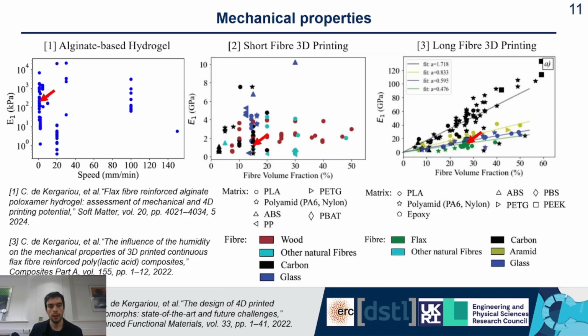So what we did is we tested different types of material for our 4D printing endeavor: alginate-based hydrogel, short fiber 3D printed and long fiber 3D printed. And we're able to see that depending on what you want, you have different types of mechanical properties available. The red arrows represent materials that we have tested for 4D printed application. We've created databases for all the similar materials that we could find in the literature. And so we encourage you to have a look at these databases if you're looking for a material.